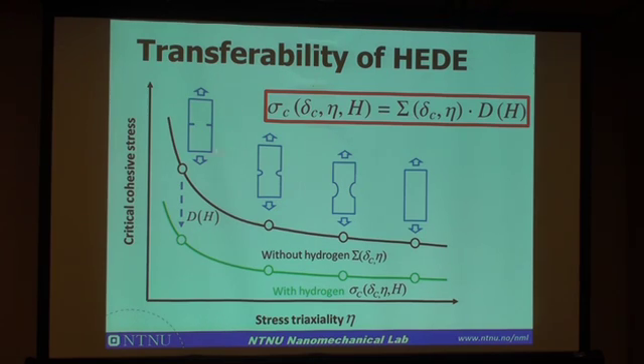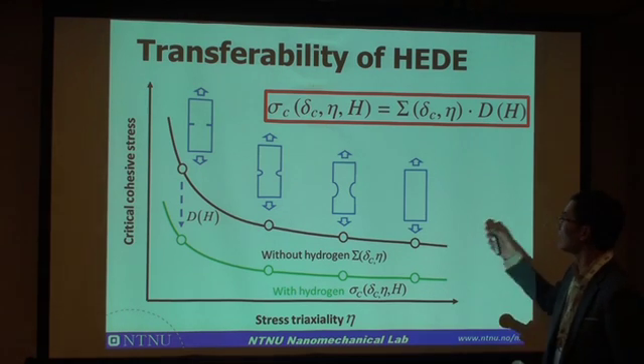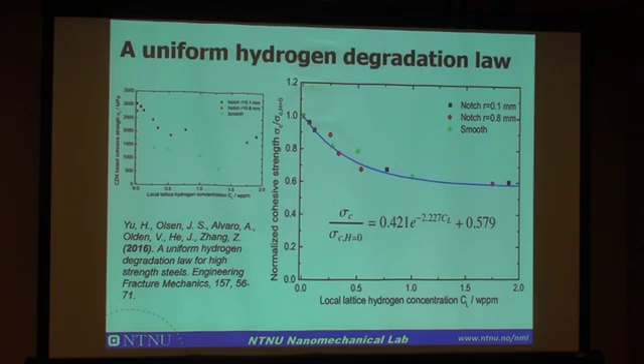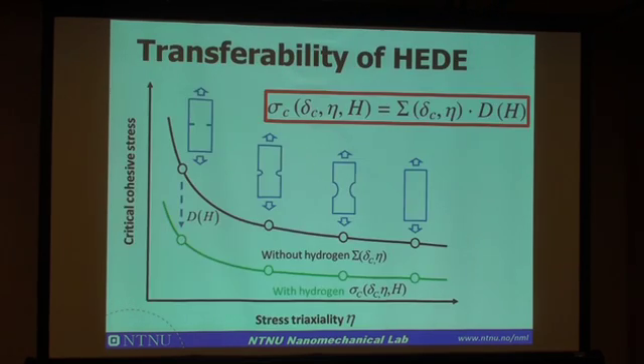So the critical cohesive stress is a function of, of course, the critical separation distance, which we have kept as a constant, and also eta, the stress triaxiality. And with hydrogen it can be expressed as a relation without hydrogen, and move everything into the D, and D is this relation. This is an empirical relation.